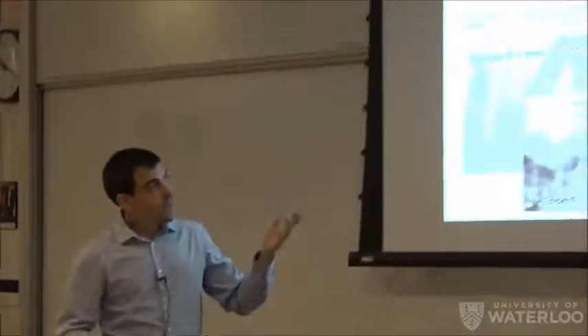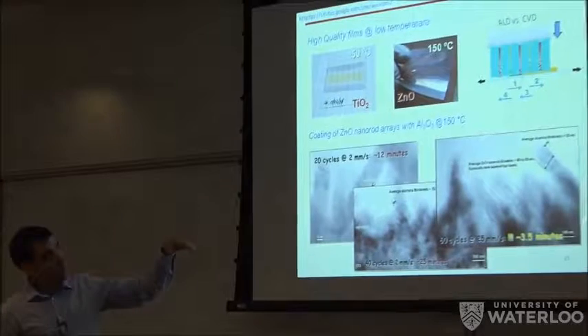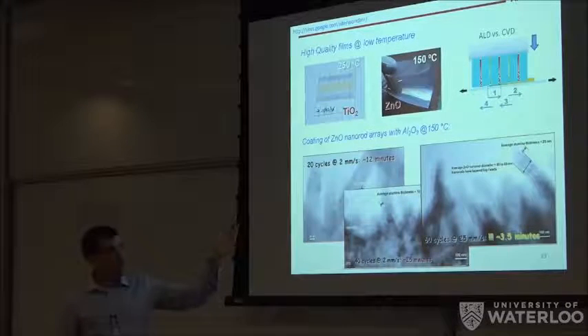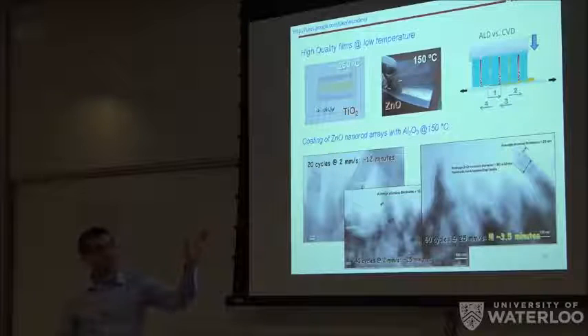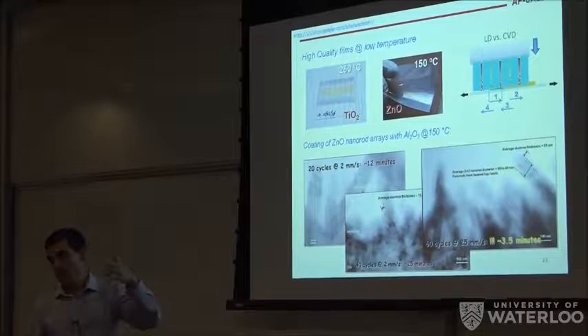Very interesting approach. I look forward to getting one here. I just have a question about the limits of film thickness when you're trying to coat a porous material? I imagine there must be some pretty strict limits in terms of how far these penetrate. Yeah, I would say that this is one of the limitations in terms of speed for this technique. Here, of course, we have a flat surface that is in direct contact with the nanowires and the gas flows. So you're going to saturate the surface very fast. You don't need to worry about this issue.